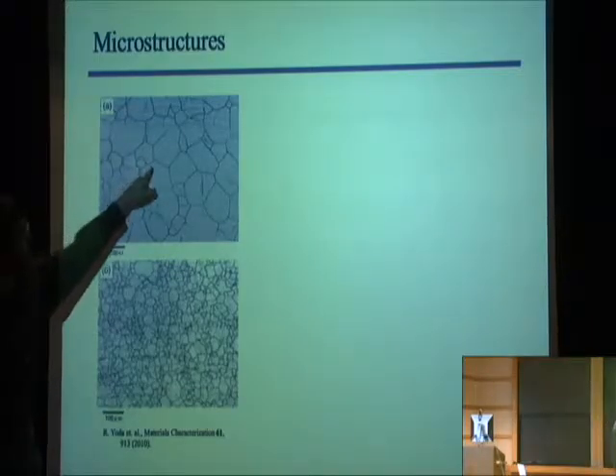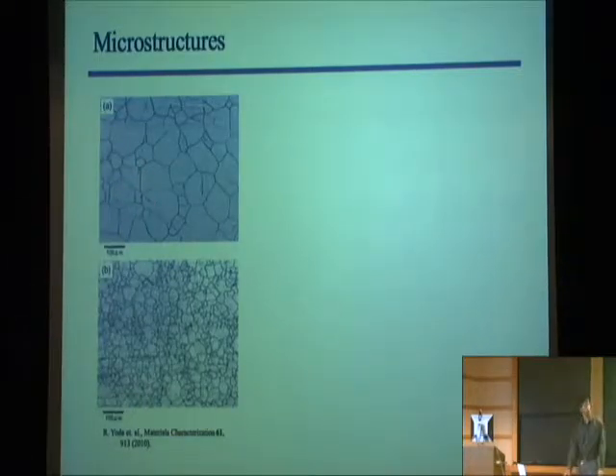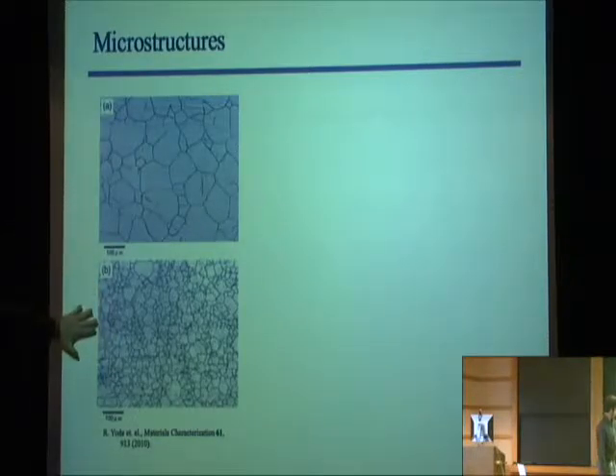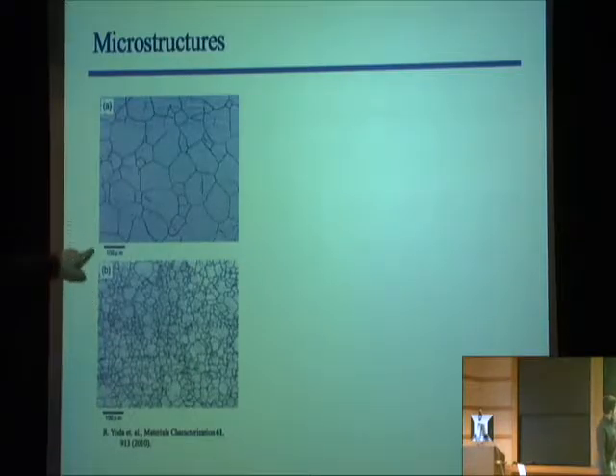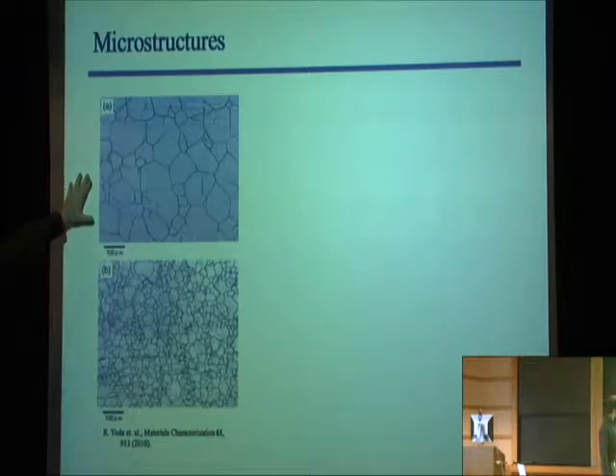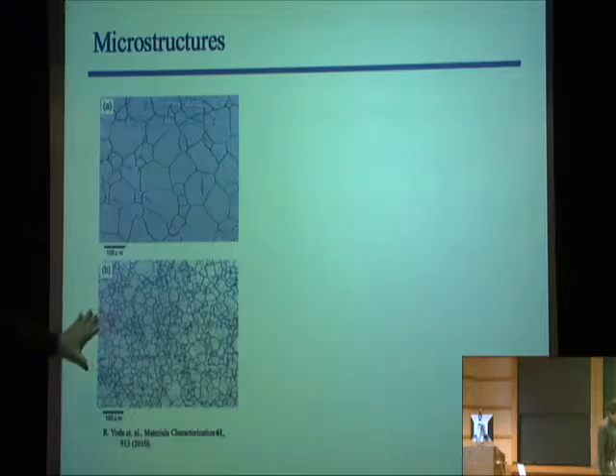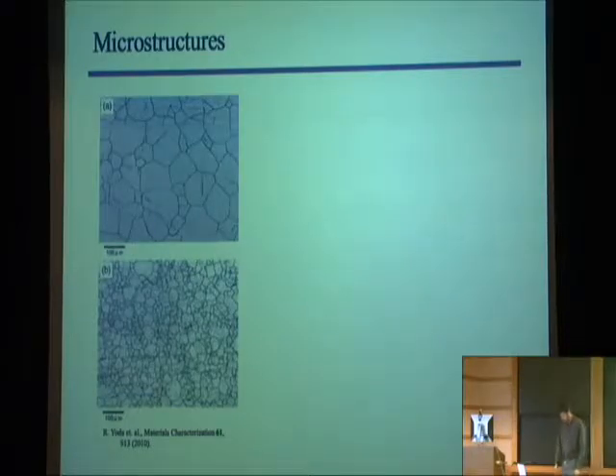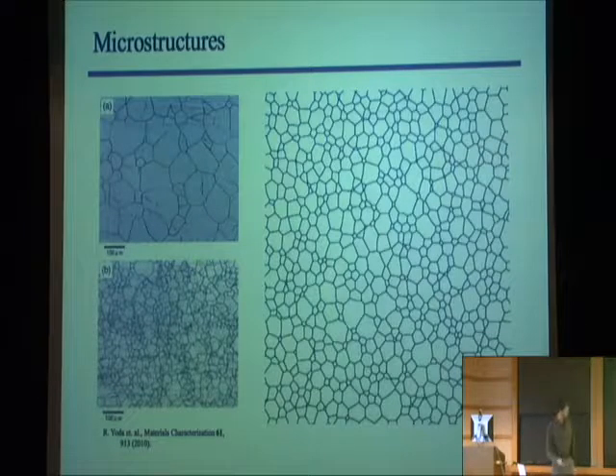We have these vertices where three grain boundaries come together. There are no vertices where you have four grain boundaries or two. What's more, it looks almost as though it's scale invariant. These are actually both from samples of polycrystalline steel. These scale bars are in fact the same, so these are at the same magnification. If you take this structure and scale it down, you would be able to superimpose it over some part of this, at least approximately in some statistical sense. So these structures are approximately scale invariant.